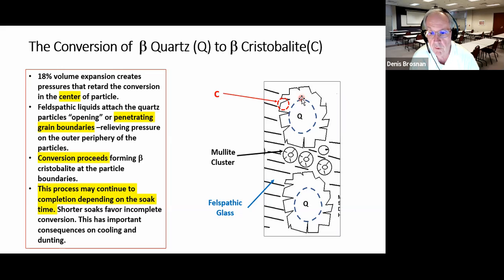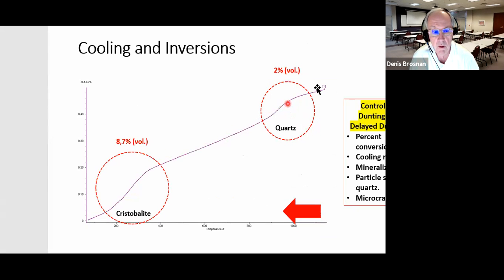I have seen it before in very coarse grain silica bodies made out of ganister silica rock. But in pottery, I don't think that we normally see that much. Of course, there is the inversion of quartz on cooling. Here we're cooling a body that contains beta quartz. So in cooling, it inverts back to alpha, and we get a little bit of a 2% volume decrease right at 573 degrees C. Because of that,